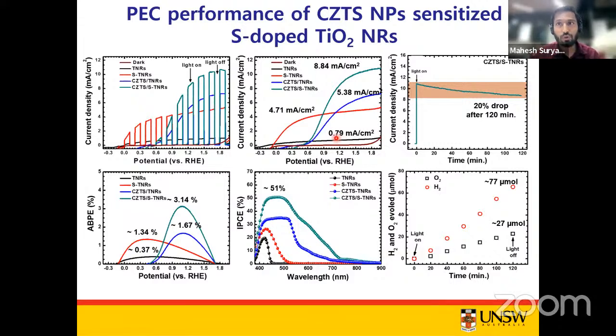Interestingly, this substantially enhanced photocurrent density in the CZTS sensitized sulfur doped TiO2 nanorod arrays is almost equal to the sum of the photocurrent densities obtained from sulfur doped TiO2 nanorod arrays and CZTS sensitized TiO2 nanorod arrays, which clearly indicates the synergistic effect of the sulfur doping and the CZTS sensitization on these TiO2 nanorod arrays. As a result of these synergistic effects, we achieved the PEC cell efficiency, also called applied bias photon conversion efficiency, of about 3.14%, which is the highest among all the samples for the CZTS sensitized sulfur doped TiO2 nanorod arrays.